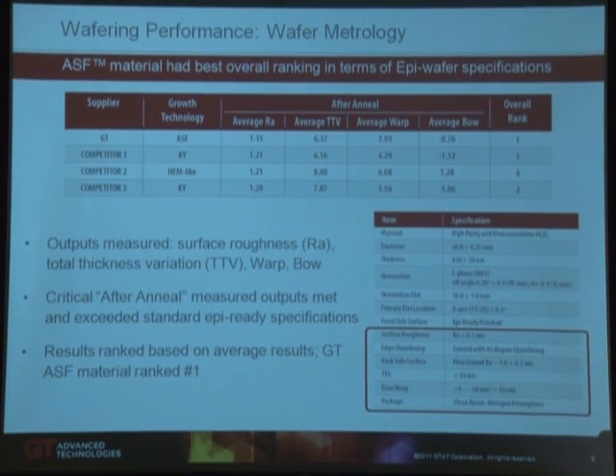Standard wafering specifications, they do a number of quantitative tests after the annealing process. And typically, after the standard annealing process used by all wafer houses to remove the stress induced by the sawing and polishing process, measurements are taken for roughness, total thickness variation, total warp, and total bow. This shows the total average results for each of the sample sets, GT and the other competitive technologies, and the average results for each of these measurements. And then we rank them based on that average. In this case, results ranked based on average results, GT ASF material ranked number 1.